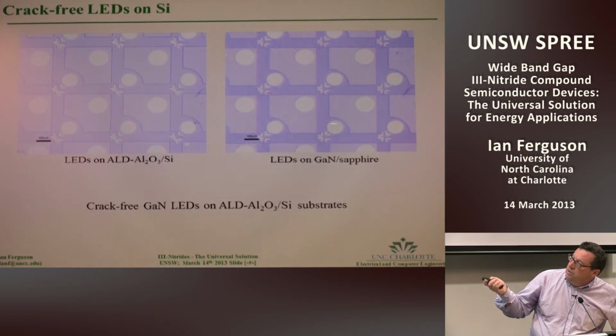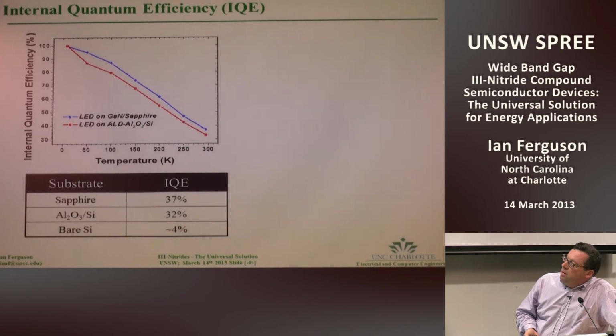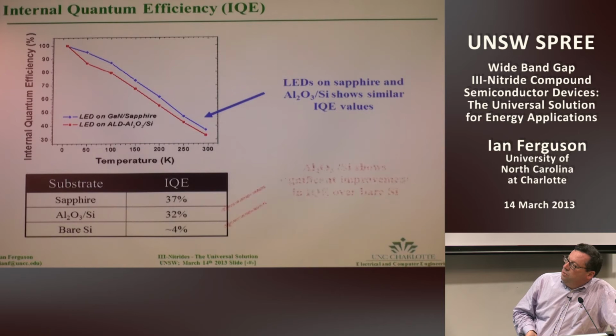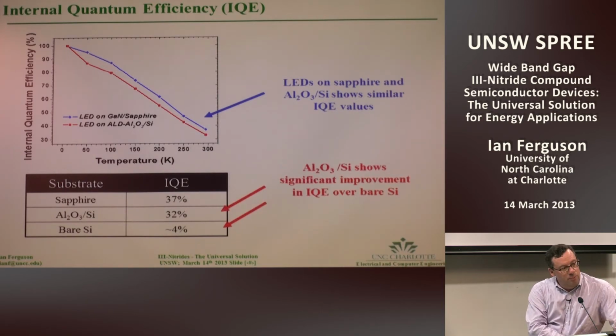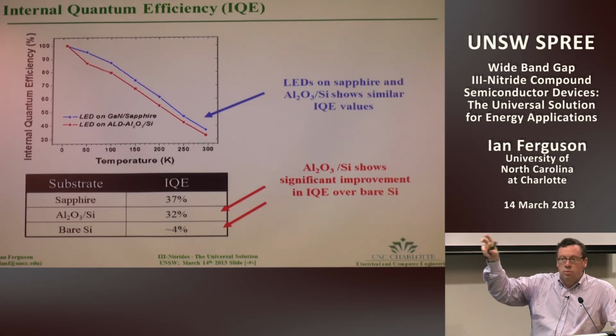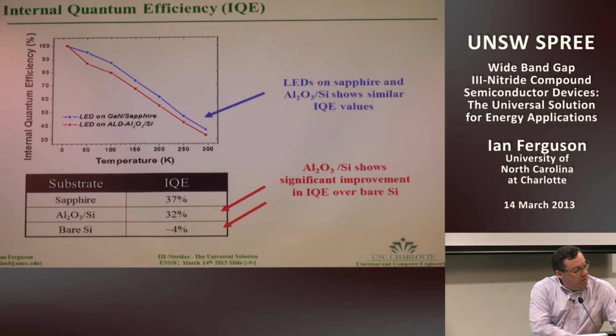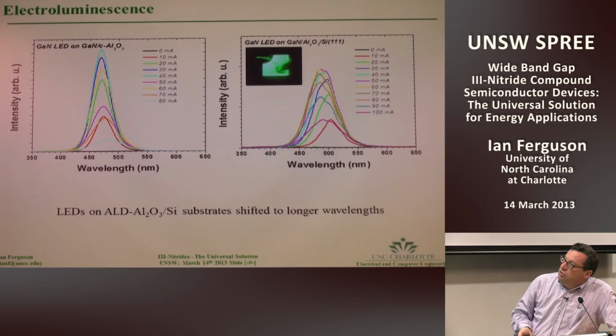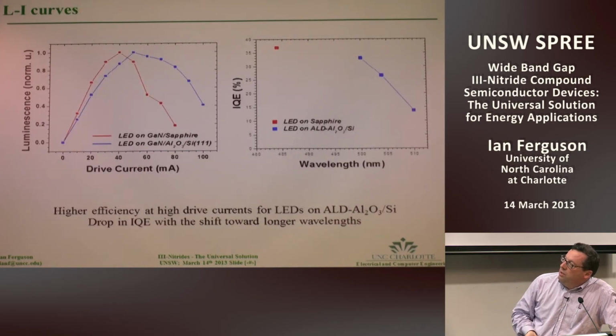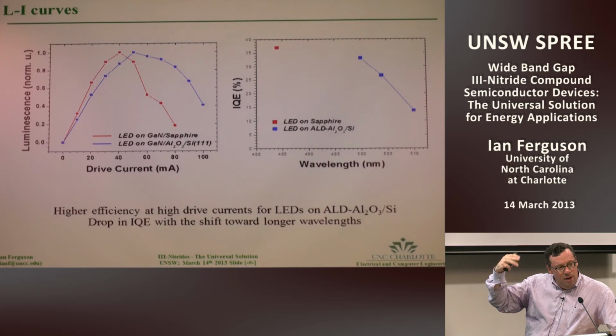So this is showing LEDs on silicon, LEDs on sapphire. These were just simple devices. This is IQE measurements for the devices. And the important thing to pull out here is that compared to bare silicon, when we did these other devices, the IQEs were somewhat similar. Again, our device structures weren't the most complicated because we were more interested in addressing the materials issues. Can you actually get the devices to work well on silicon? So this is showing the LEDs, both on aluminum oxide, both on sapphire and on silicon. And typically what you would find is that the devices on the silicon were somewhat similar to the ones on sapphire, but they would tend to degrade as we went out in wavelength. But that's typical for the LED structures, which you'll see later on when I talk about solar cells.